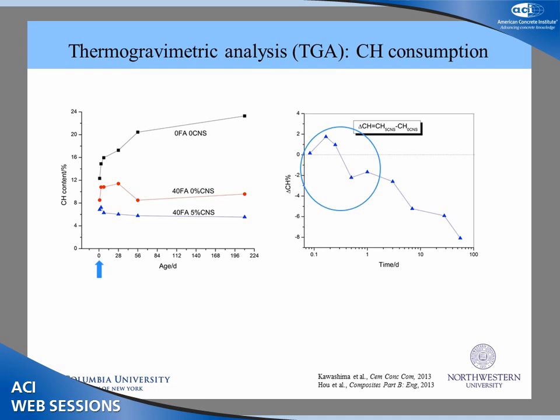Now, if we just zoom into the first day and look at the CH content within the first 24 hours. Now, this is a plot of the difference in CH in the 40% fly ash cement paste with 5% colloidal nanosilica and then 0% nanosilica. And we see this initial spike, and that's capturing the seeding effect of the nanosilica. Now remember, in a few slides earlier, nanoparticles have different effects, and this is the seeding effect. But then, immediately, it's followed by a decline, and that's due to the increased pozzolanic reactivity of the nanosilica, so it's starting to consume CH. So these results help to explain why the nanosilica is helping to improve the early age strength gain.